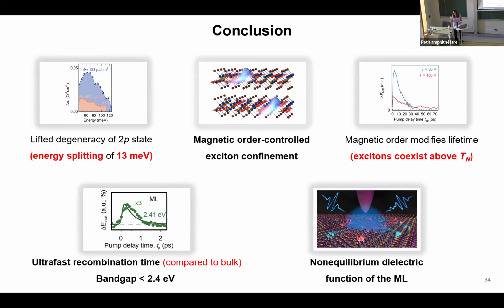And also when you sharpen the tip so much that you have this nanoscopic resolution, you generate so few electron-hole pairs. This contributes to even increasing the measurement time. Here we estimated that we generated a few tens of electron-hole pairs. This is so low, but still with the stability of our measurements, we could still get some ultrafast response out of them. But the spatial mapping, this is what our terahertz STM people did. I can send you a paper about how they detected the defect, but I don't know how long they accumulated actually. Thanks. Any other questions?